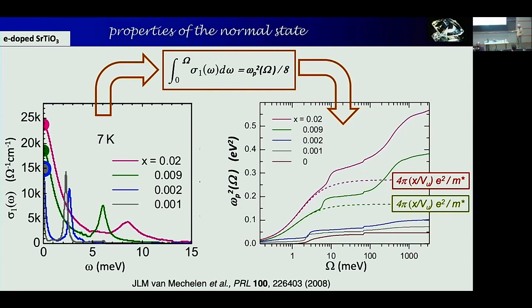I'll say a lot more about this phonon because that's the soft ferroelectric fluctuation of your system that is very sensitive to everything. It's sensitive to temperature, it is sensitive to what you dope your material with, and so if you put in dopants, then actually it shifts up in frequency, and moving up in temperature also makes it shift up. But the important thing here is actually this peak, the Drude peak.